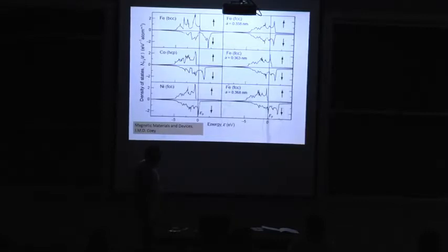But iron isn't. Look at iron BCC. Iron FCC. Iron FCC with a certain unit cell, 0.358 nanometers at certain pressure, temperature, etc., is not ferromagnetic. But the same iron FCC structure under different conditions with a different unit cell.